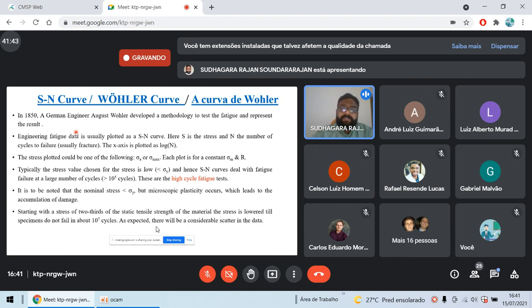Okay, so starting with a stress of 2/3 of the static tensile strength of the material, the stress is lowered till the specimen does not fail in about 10^7 cycles. We usually take 10^7 cycles. So if it is so, the material is said to be fine. So there is no failure up to 10^7 cycles, then that particular stress amplitude is considered to be the fatigue limit of the material.